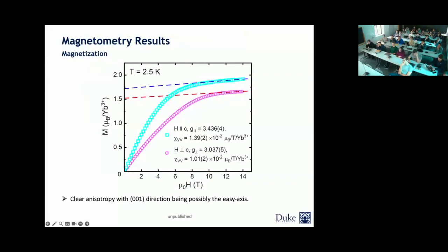So to better understand the anisotropy, we also did magnetization measurements. Here you're looking at M versus H up to 14 Tesla, collected at 2.5 Kelvin. It was for us to see when you have a strong enough magnetic field to polarize all the spins, and also to look at the anisotropy. You can see that for the two different orientations of the field, there's a clear anisotropy. And I would say at around 10 Tesla, both directions start to have the spins polarized as a function of field.